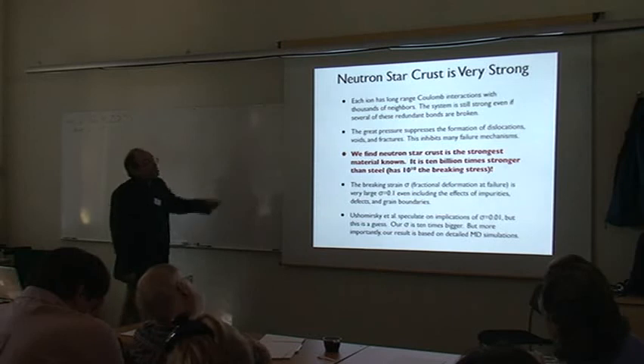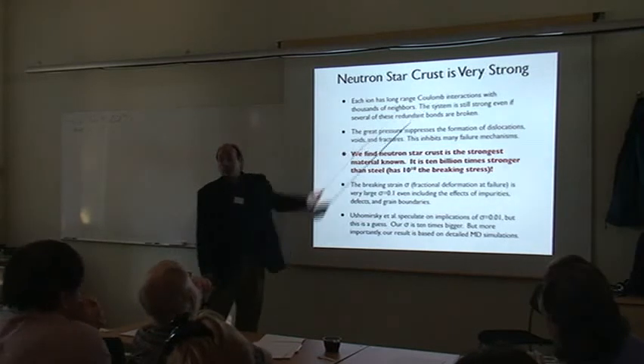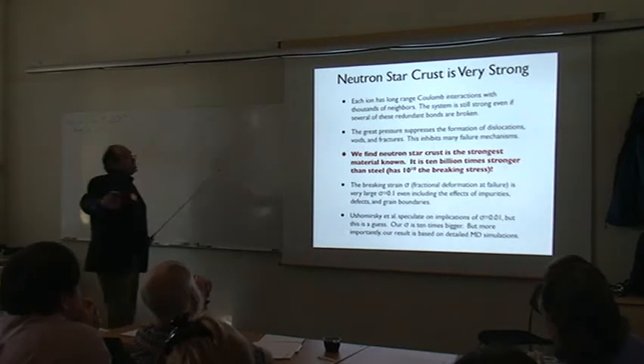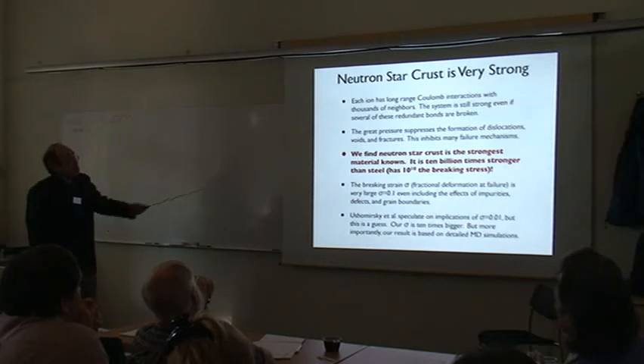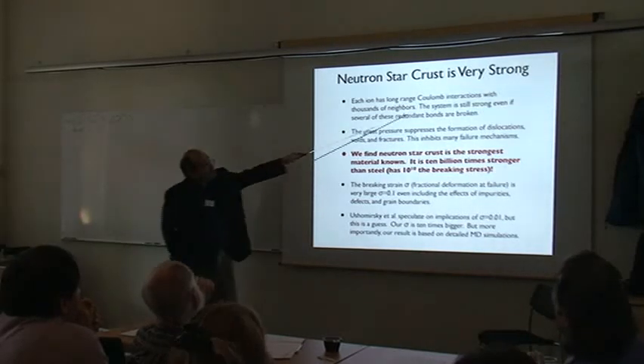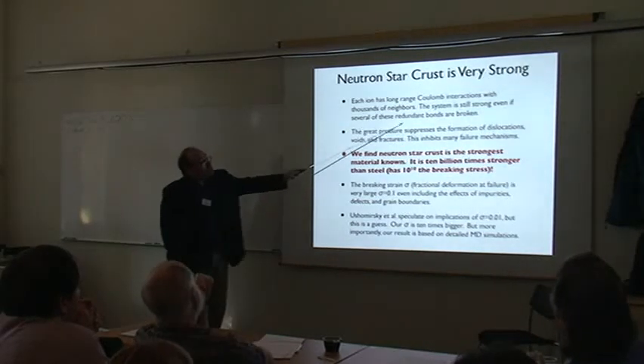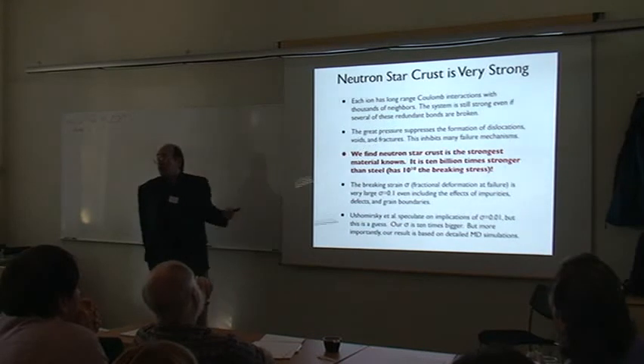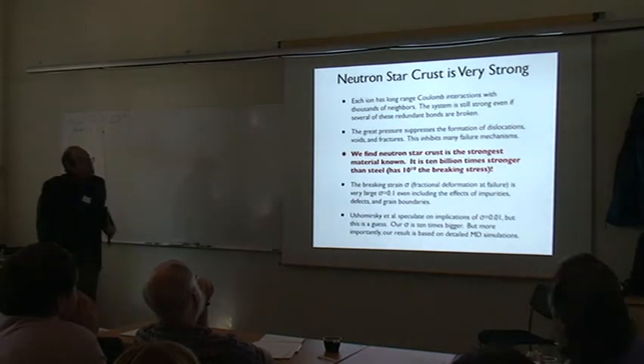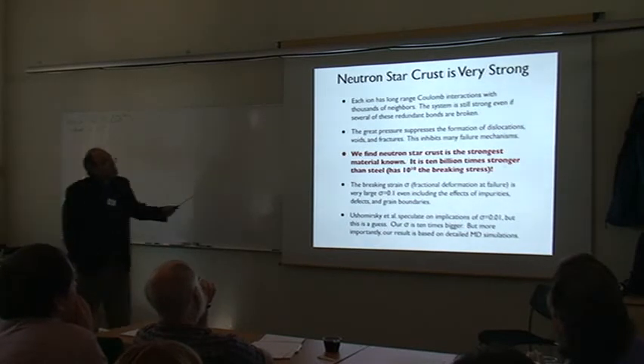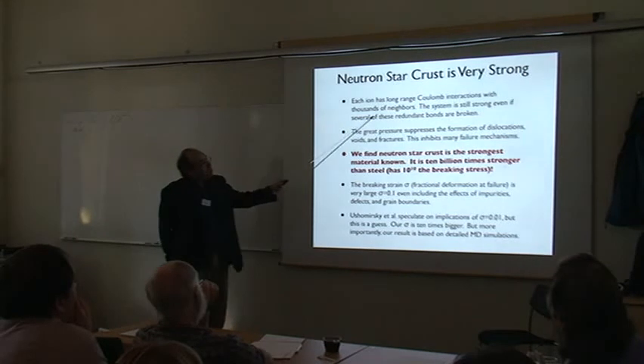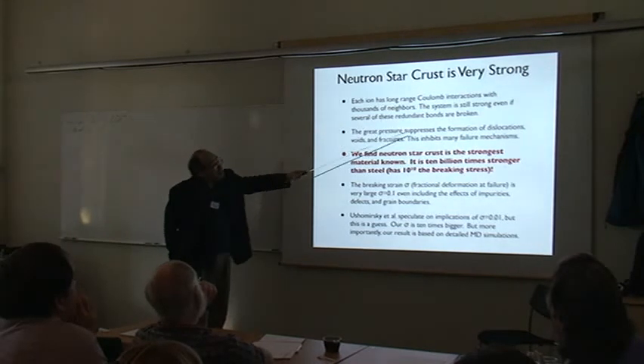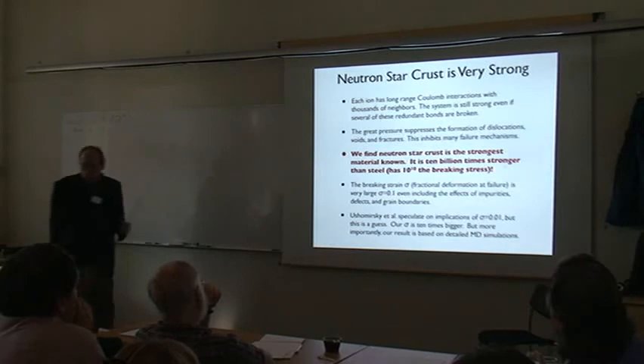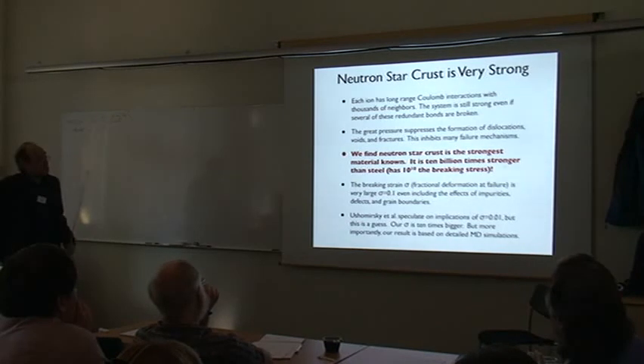At the same time, you have long-range Coulomb interactions. Each ion is interacting with thousands of its neighbors. The system is still strong even if several of those redundant bonds are broken. So if you have some local defects, break some of the bonds, you still have lots more interactions which hold the system together. The long-range Coulomb interaction and the high pressure lead to a very strong system.